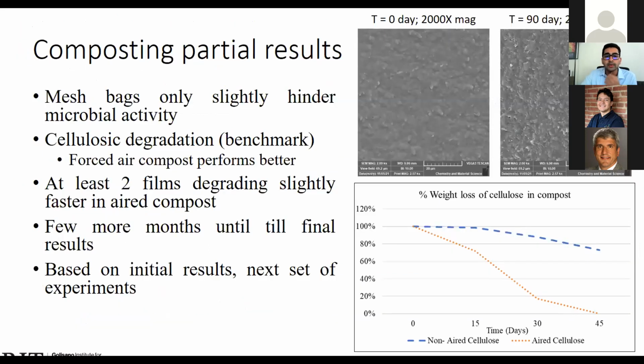And some results which we got from our composting trial were, first, the mesh bags only slightly hindered microbial activity, and second, for cellulose biodegradation, which we generally use as a benchmark, we saw that forced-air compost performed better. These 2 points are seen here. If the mesh bags had hindered the biodegradation of cellulose, we would have seen a much slower loss in weight of the cellulose, but we do see a quick weight loss in cellulose, similar to what we see in soil.